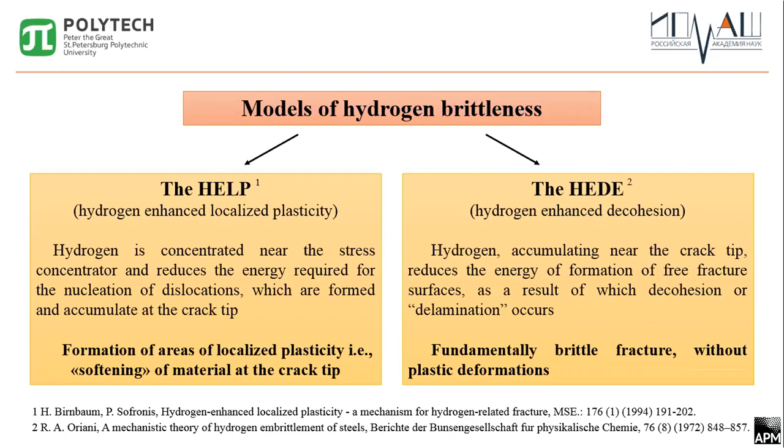With the development of this research, it was found that the fracture surfaces of destroyed samples have a non-uniform fracture pattern. Brittle fracture occurring according to the mechanisms of hydrogen embrittlement gives way to ordinary fracture, which does not have pronounced hydrogen signs. This fact induced researchers to use the combined HELP plus HEDE approach. But the authors note the existing problems with the determination of many model parameters and point out that the simulation results are only in qualitative agreement with the experimental ones.